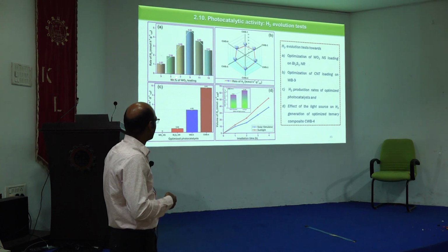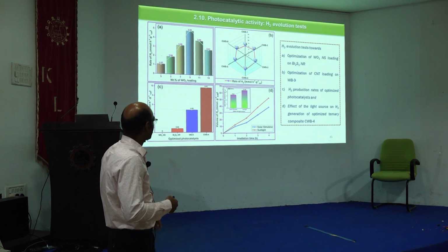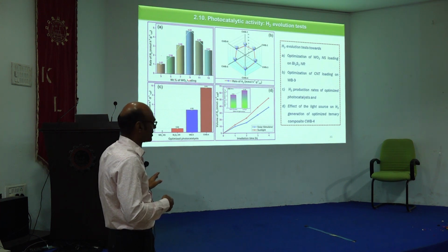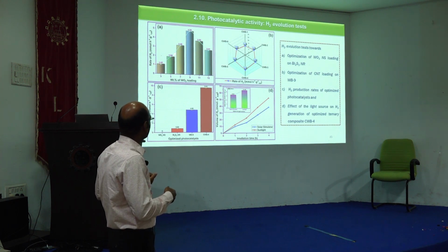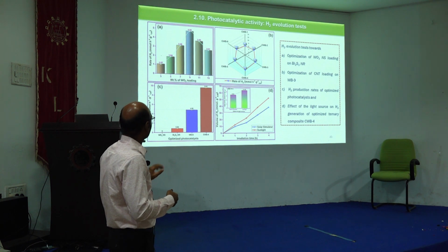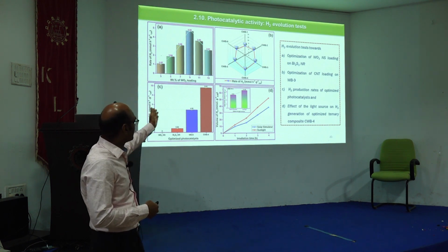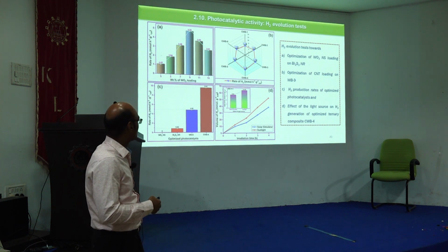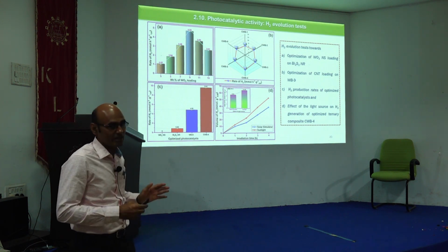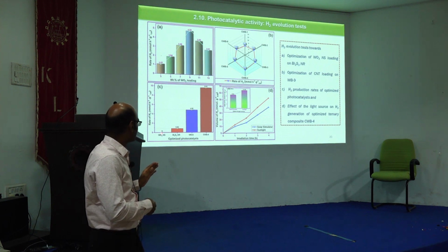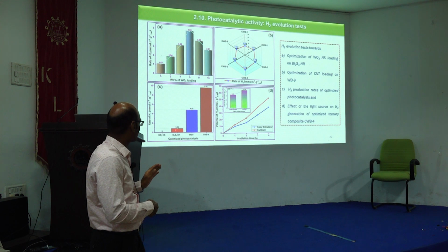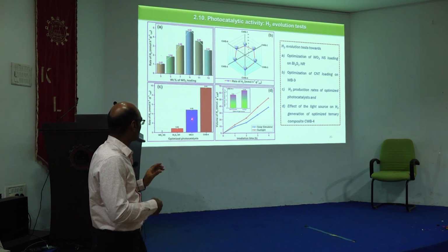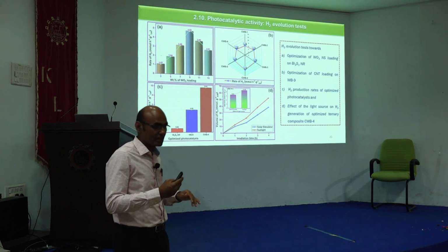On the x-axis you can see the weight percentage of tungsten trioxide loading on bismuth sulfide, against the rate of hydrogen production. It shows that the rate of hydrogen production increases with tungsten trioxide loading, which we varied from 3 to 13 weight percent. At 9% it shows 4.95 millimolar per hour per gram of catalyst. You can see how the ternary catalyst performs, and if we compare the efficiency of the different materials, the pristine material shows no hydrogen production, whereas bismuth sulfide shows very little. Binary shows very good, and ternary shows excellent hydrogen production.